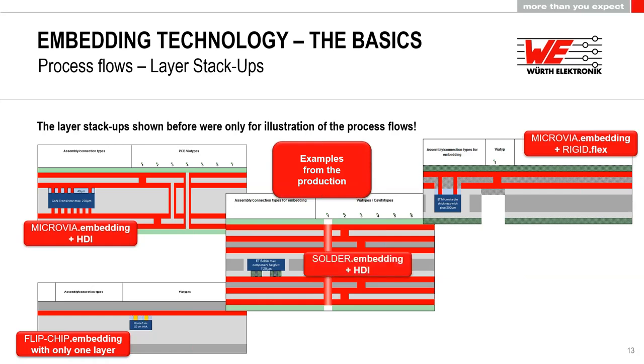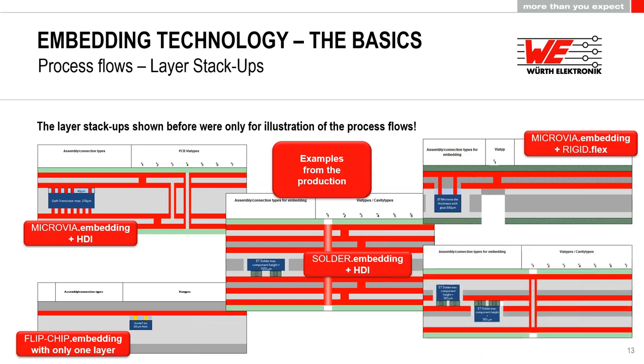which we have combined again with several microvia layers. These microvia layers could either be used for your fan-out of the component to be soldered onto the inner layer core, but they can as well be used, for example, as a heat path. You see that we could make, for example, the microvias directly into a ground pad of a component and then get the heat out of the component through the ground pad directly to the outside of the PCB by using two copper-filled microvia layers, as shown in this case here.